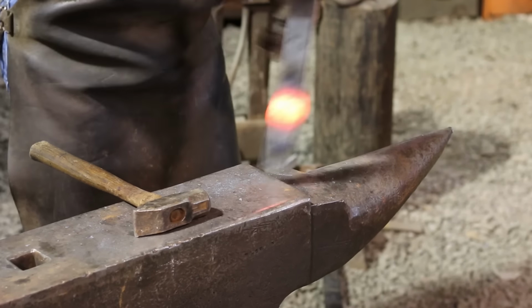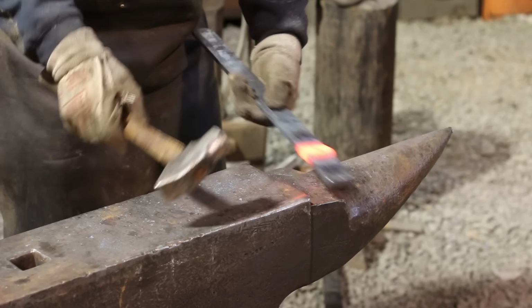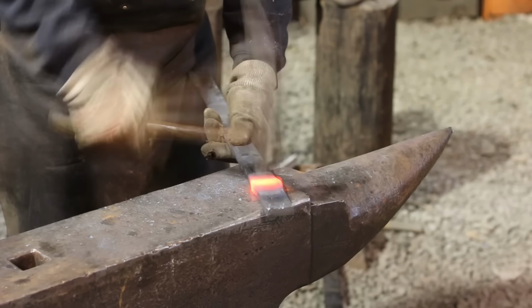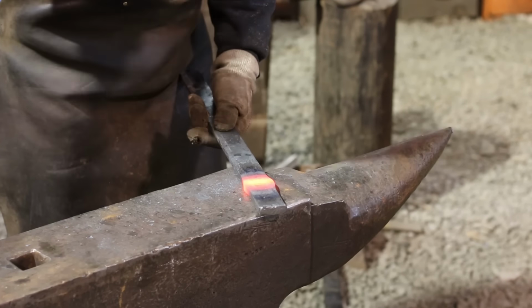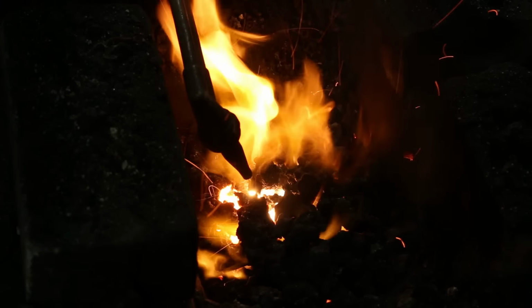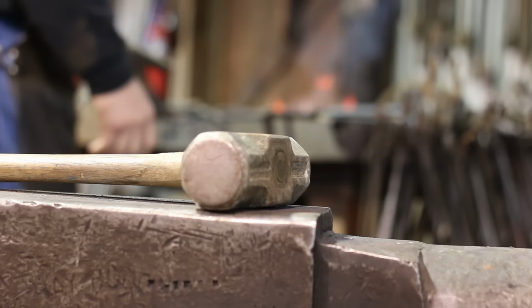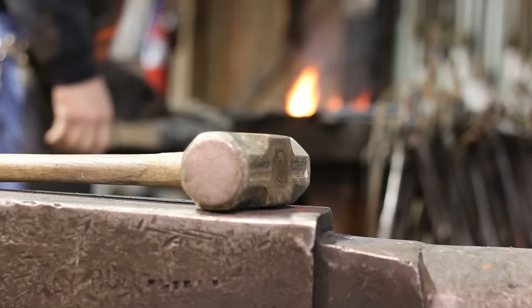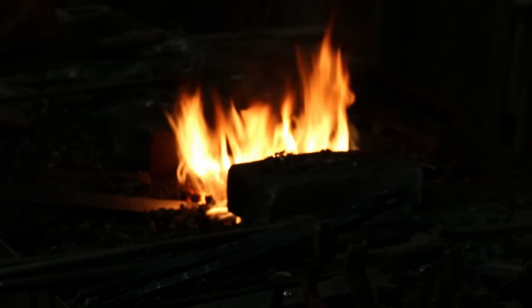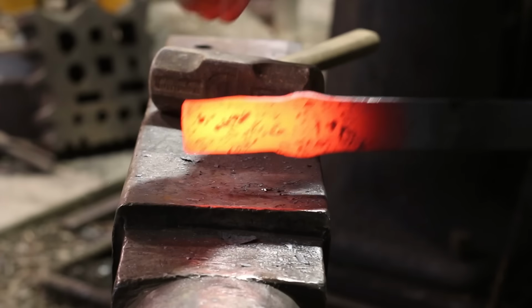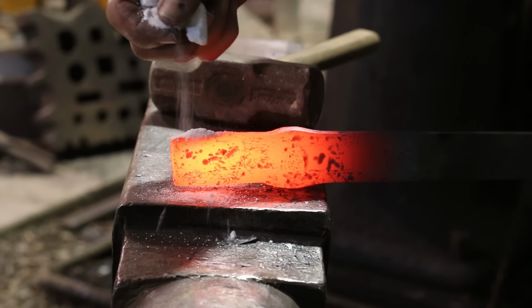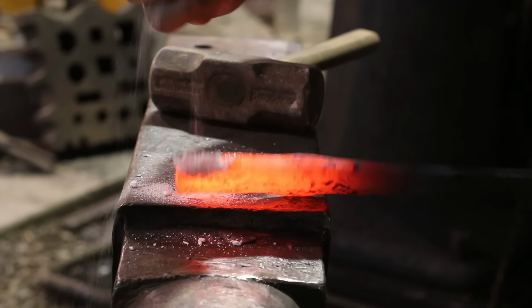Next, I started drawing out the tang for the handle. Now, like I said, this is a Damascus or pattern welded steel, and I spotted a delamination, or a separation between the layers, starting. So as I begin to reduce the cross section of the handle end, I'm going to start just gently, by hand, at the anvil, and then I'm adding a little flux to try to re-weld the flaw in the next heat.